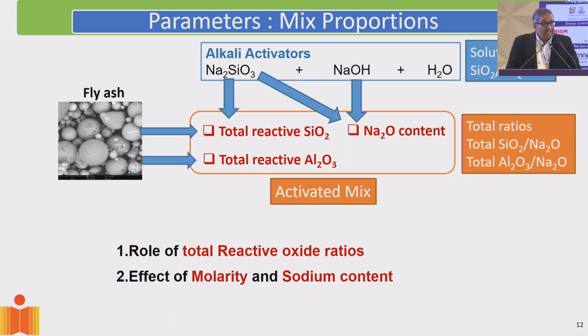Now, what you get in a geopolymeric system is much more complex than what you see in a cement paste, because in cement paste, you only deal with the water to cement ratio. What you have here are the reactive ratios. You have the silica to sodium ratio and the alumina to sodium ratio, in addition to the molarity of sodium hydroxide. So you have to play with all three of these things to figure out the optimal ratios, which are based on the reactive content that is coming from the fly ash.